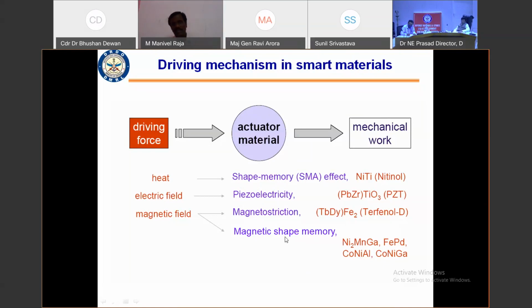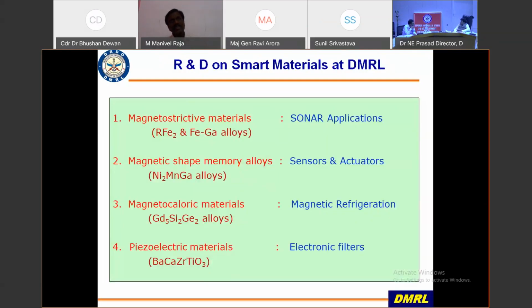As I was telling, there are two types of shape memory. One is thermal shape memory, that is nickel titanium, whereas the magnetic shape memory is again a nickel-based alloy: nickel, manganese, gallium. There is no temperature involved here. By applying a magnetic field, you can change the shape. So the driving force is the magnetic field instead of temperature. This is the kind of activity going on at DMRL. We have taken up R&D projects on these smart materials.